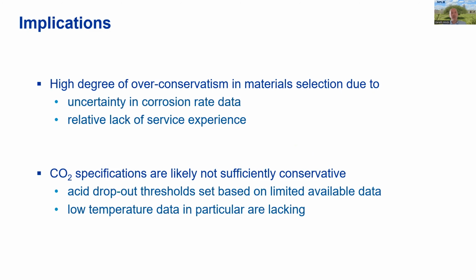So finally, just to step back a bit and ask the question, what are the implications of all of this on CO2 transport? Well, firstly, at the moment, because of this lack of consensus on corrosion rate and mechanisms and how phase behavior affects corrosion rate in particular, operators need a high degree of over-conservatism in material selection. This means selecting a more expensive material in situations where you don't have enough information on the corrosion rate and there is a relative lack of service experience. So projects that are being delivered now are probably overcosted because of this over-conservatism. This will have to change in the future with more research and with more understanding of these different mechanisms.